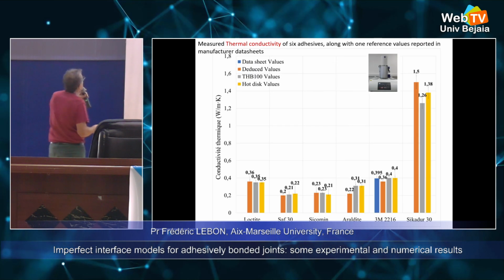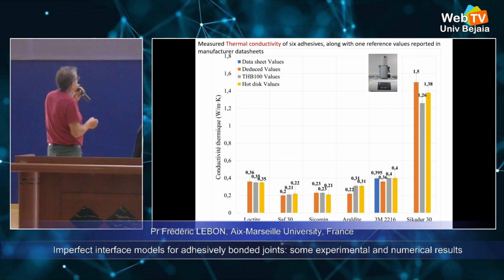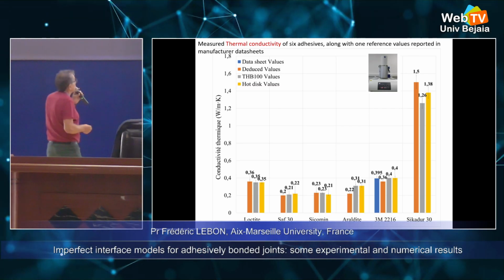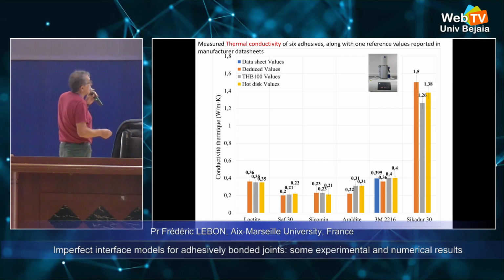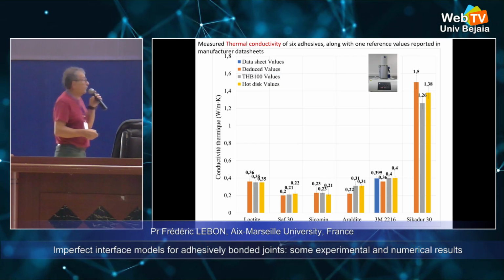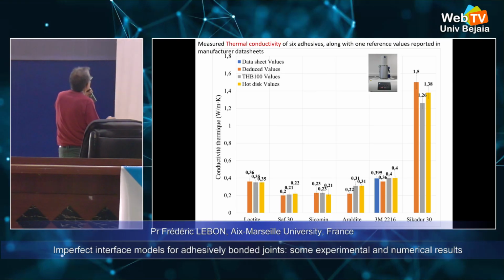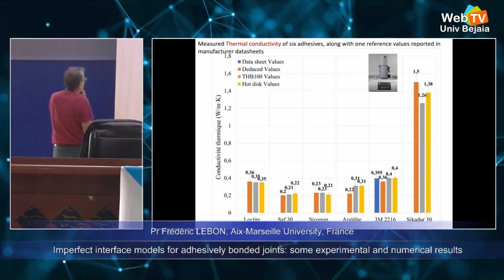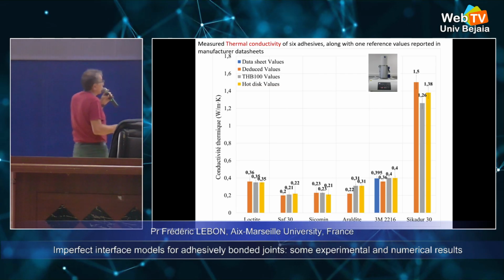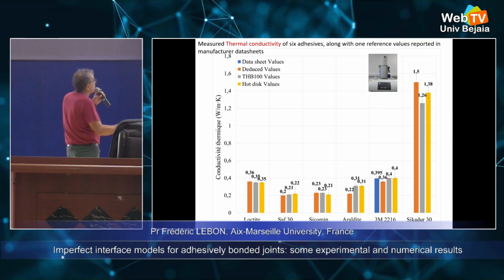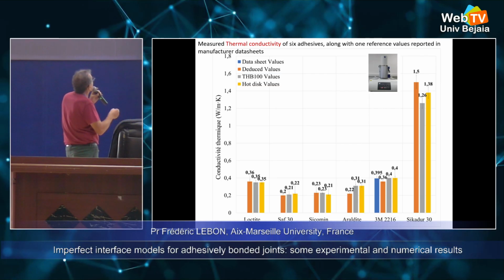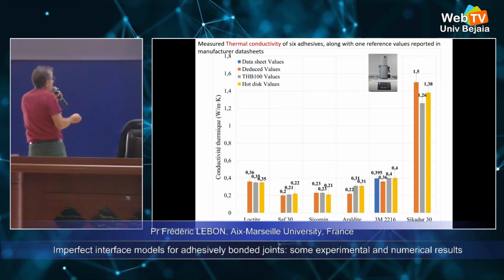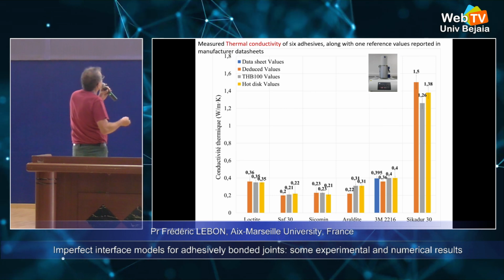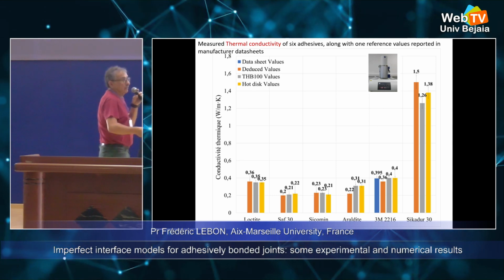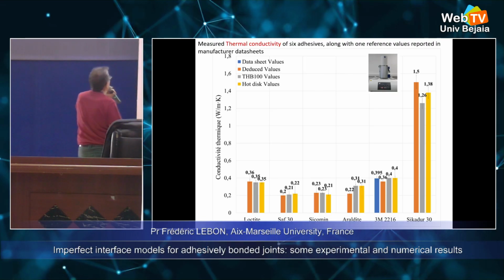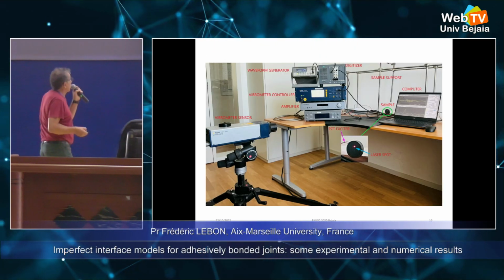We can do the same for the thermal conductivity for the 6 adhesives. Here there is only with these 3M that we have the industry results, and we have 3 experiments to compute this, and we can observe that the Sikadur is very different from the other ones for this parameter. Okay, and if we want to have a thermomechanical model, it is very important to have this kind of parameter. And we have another experiment.